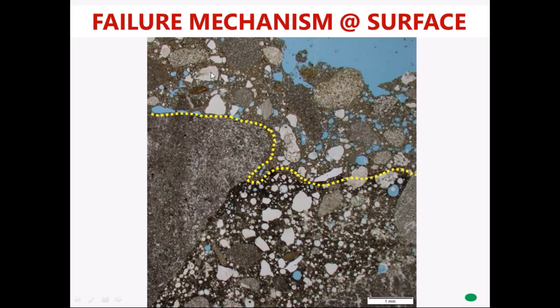The more water in that paste, whether it rained on the concrete when it was placed and got a bunch of water on the top, whether it was finished incorrectly, whether the contractor bled it too much and they were trying to finish it. I don't know what did it, but too much water in the uppermost paste made the paste weak and easy to just flake off, and there's no strength to it.